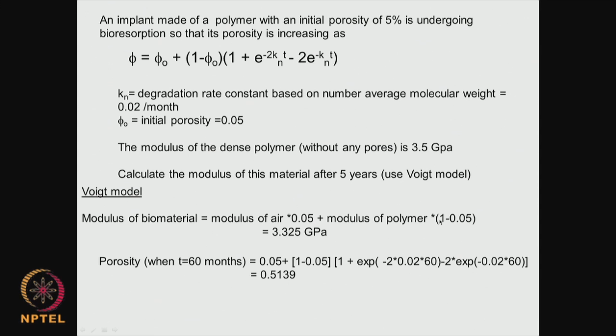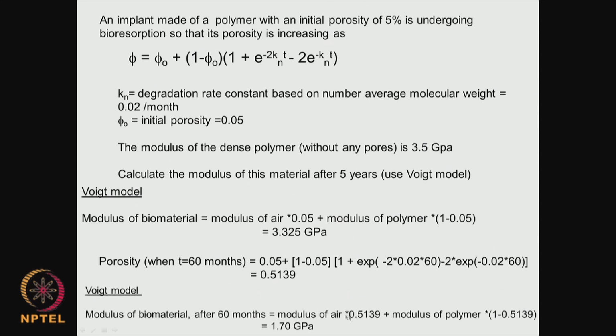Now, we need to put it in the Voigt's model, so that 51% will not contribute to the modulus of the biomaterial, the remaining 49% will contribute. So, the modulus of the biomaterial after 60 months is modulus of air into 0.5139 plus modulus of polymer into 1 minus 0.5139, that gives you 1.7 gigapascal. So, what has happened? The modulus of the biomaterial has gone down in 5 years from 3.3 gigapascal to 1.7, almost half. So, is it desirable? That is what you have to see.